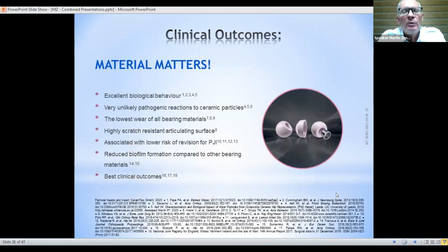So this brings me to the conclusion of the first part of my presentation. We believe that by using ceramic components, material matters in view of clinical outcome. We have an excellent biological behavior of the ceramic. It has very unlikely pathogenic reactions to ceramic particles, the lowest wear of all bearing materials, and a highly scratch-resistant articulating surface. It is associated with a lower risk of revision for PJI. It reduces the biofilm formation compared to other bearing materials. And this comes now to the end of my first presentation.